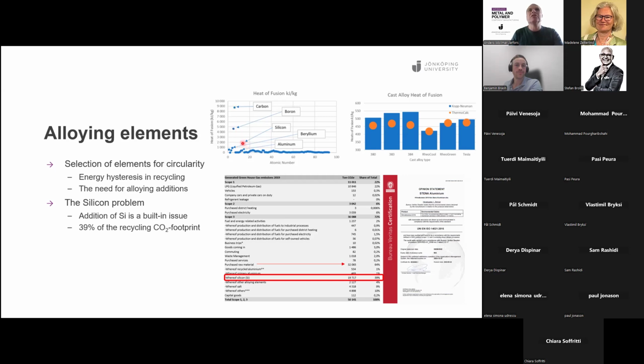But silicon is really an exception here. It has a very high energy of melting, and this is reflecting what Benjamin said in that it has an effect on the LPG usage. And by choosing high silicon alloyed materials, you build in an energy hysteresis in the recycling. So every loop you recycle the material, it takes more energy.